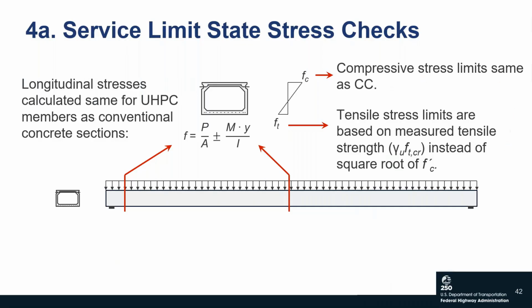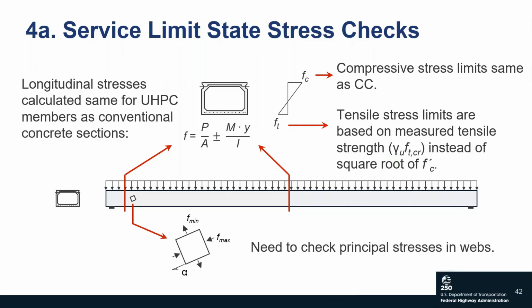Because you're measuring the tensile strength during the material qualification process, you can use that cracking strength as your tension limit instead of a value that's based on the compression strength of your material. The other slight difference is with UHPC, we're going to have narrower webs and less shear reinforcement. So we need to make sure that our beams don't crack under service loads. Because of that, we need to check the principal stresses in our webs. And we'll do that using the principal stress checks that are typically only used for post-tensioned members.